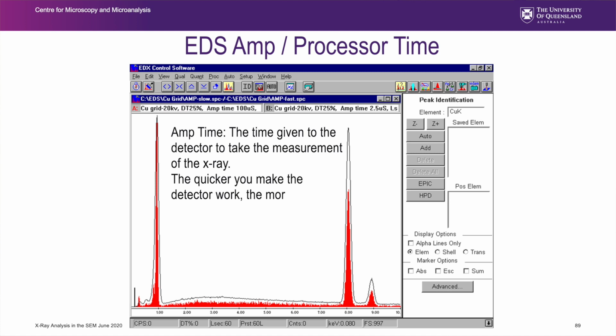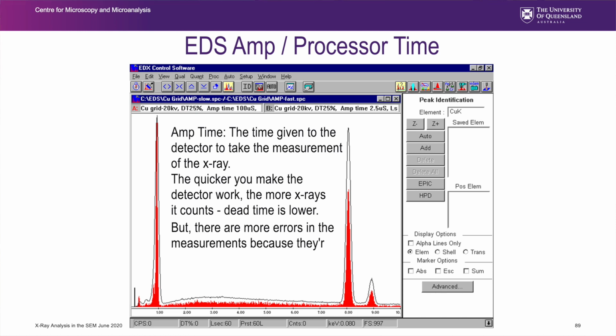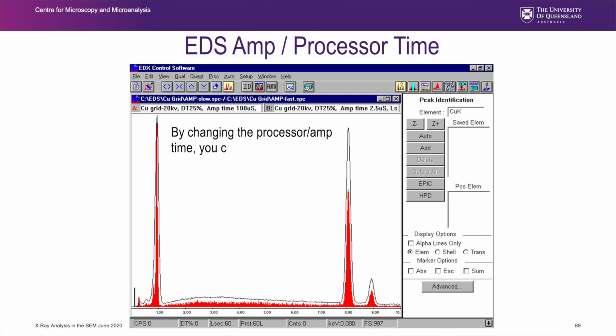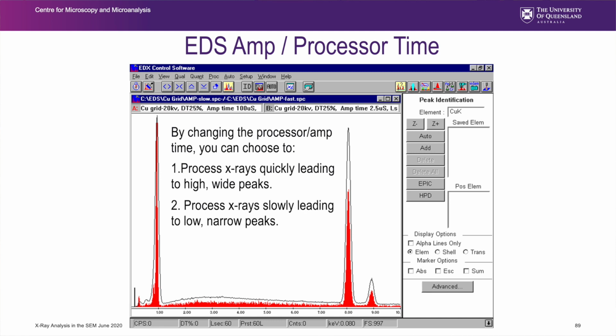The quicker you make your detector work, the more X-rays it counts, so your dead time is lower. But because it's got to count those X-rays quickly, there's more error in the measurement, so the peaks are wider. And by changing the processor time, or the amp time, or whatever they choose to call it, you can choose to either process X-rays quickly for high peaks that are a bit wider, or process X-rays slowly, which will have a higher dead time, therefore lower peaks, but narrower peaks because you measure the X-ray energy better.